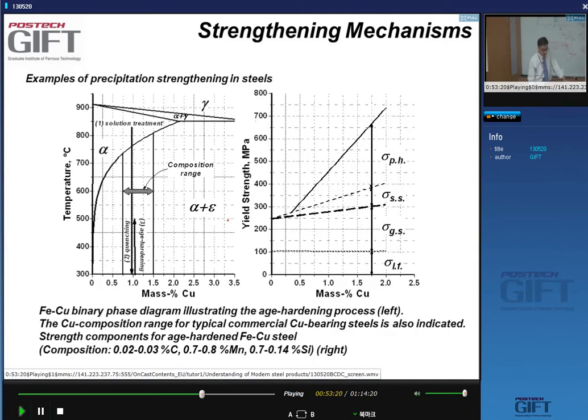How is it brought in, this copper? Well, what you have typically in these steels, this is the phase diagram, the iron copper phase diagram. The range of copper addition is 0.75 to 1.5. That's the range of copper additions that you have. What you start off with is doing a solution treatment. That means you heat the steel up to here, 850. That brings you in this alpha stability domain. You see the copper is fully dissolved in the ferrite, and then you quench the material.